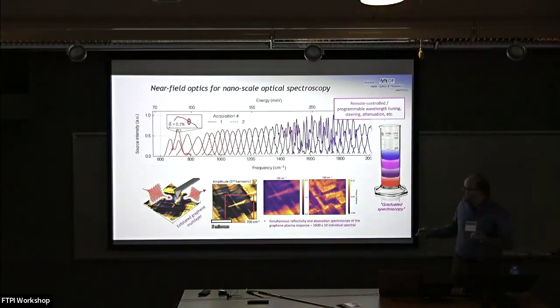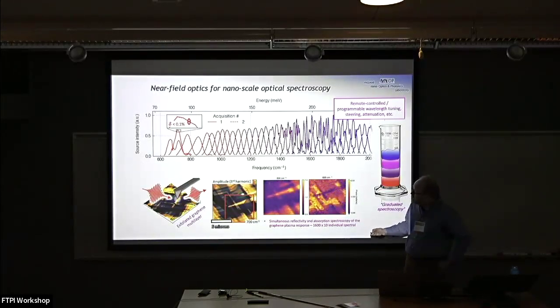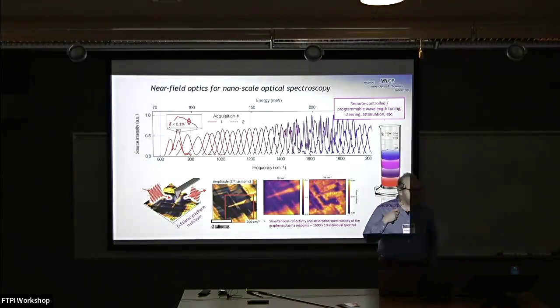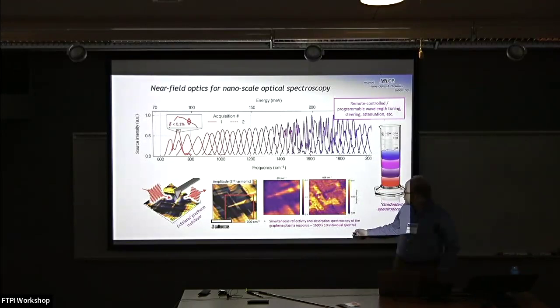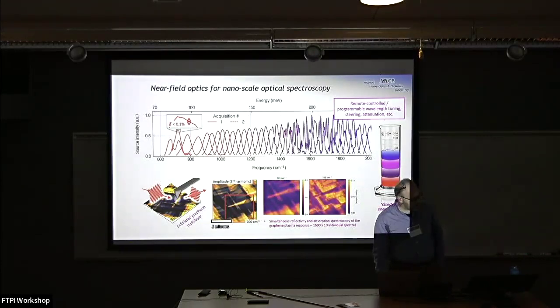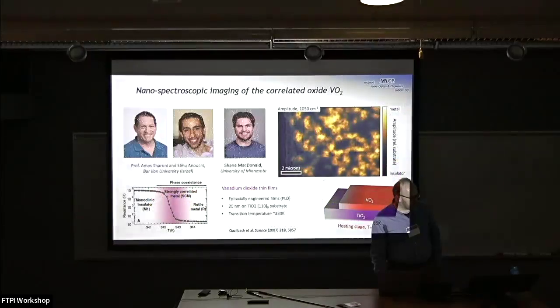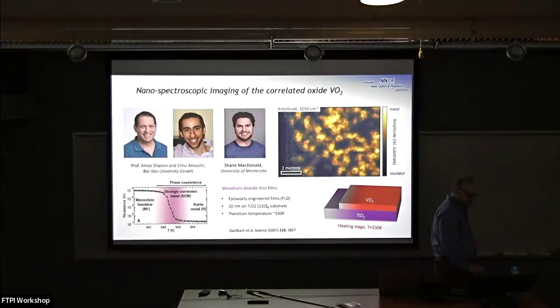So then what can we do besides acquiring images like this? We can acquire spectroscopy. So going pixel by pixel, let's say through this range right here, acquiring a spectrum at every single pixel provides a means of extracting the optical content quantitatively. And I'm showing here both the reflection contrast as well as the absorption contrast. And I can tell you how we gain access to those two individual responses of the material, which are key to go back to the complex valued optical constants.